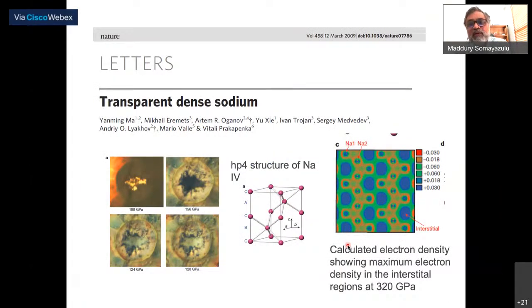Now, on the other hand, what I wanted to talk about is the interesting part, the counterexample, that something which is metallic can become insulating. So it is almost counterintuitive. This is a brilliant paper which came out in 2009, which talked about how sodium becomes transparent at increasing pressures. You can see from the pictures here that at lower pressures sodium is metallic and reflecting. As you go to higher and higher pressures, especially at about 150 GPa, it becomes black, and above 180 or 200 GPa, it becomes transparent.